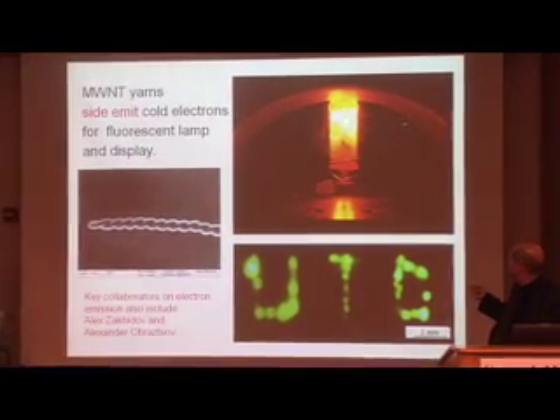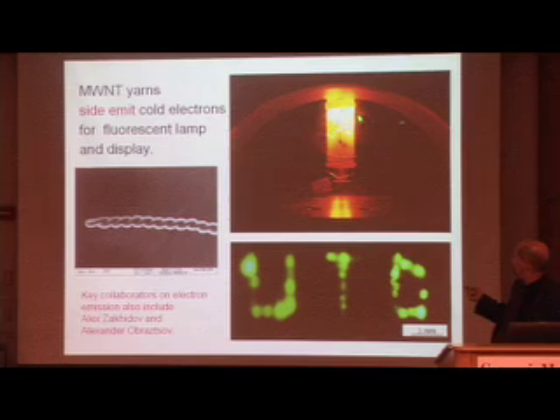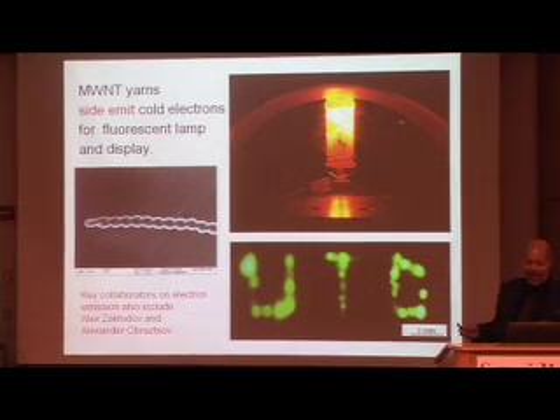We can take these carbon nanotube yarns and make intense lights from them just by putting a nanotube yarn in the middle of a cylinder that has fluorescent material on the surface of it and a current collector. You get two different types of voltage amplification effects. One is due to the fact that all the field lines are converging on this filament, but also the filament has little hairs sticking out of it. And these hairs give you a second type of field amplification effect, which allows you to operate the lamps at low voltages.